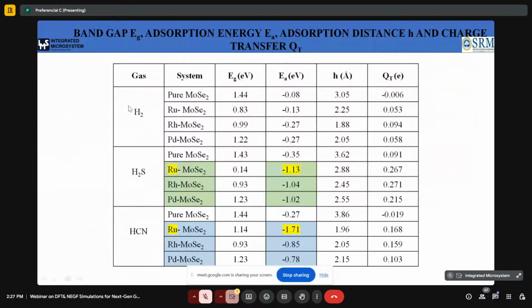If you see the hydrogen adsorbed systems, here the adsorption energy values are very low in negative magnitude. That is, the values are very small, minus 0.27 and minus 0.13. So I'm not getting a good adsorption energy value in the case of hydrogen gas, which implies the pristine MoSe₂ as well as the doped systems are all showing a very weak adsorption towards hydrogen gas, since the charge transfer is also very less in the case of hydrogen systems.